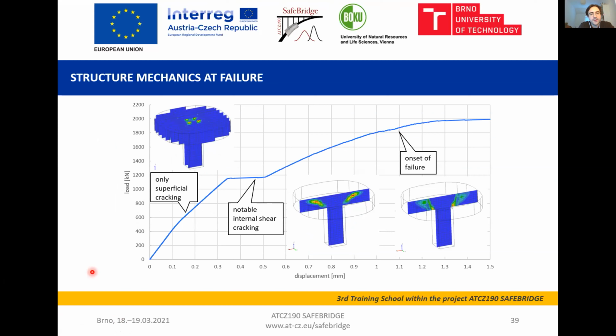Okay, so this is how the model fails. If we look at it, we can see initially we only have superficial cracking on the top, which is not structurally relevant. Then in the second image, we can see the shear cracks forming, and the shear reinforcement being activated, where we can also see this jump in displacement where the load doesn't increase, but the displacement increases by a fraction of a millimeter when the reinforcement is activated.